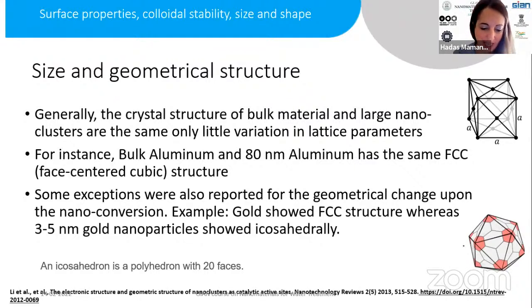So there are also other parameters that are very important to discuss. Generally, the crystal structure of bulk material and large nanoclusters are the same, with only little variation in the lattice parameters. For instance, bulk aluminum and 80 nanometer aluminum have the same face-centered cubic structure, okay? But there are exceptions to this. For example, when we look at gold, it showed an FCC structure, but 3 to 5 nanometer gold particles were icosahedral, okay? So this was the structure of the gold nanoparticle compared to the bulk gold particle. So with gold, it did change its structure to a polyhedron with 20 faces.